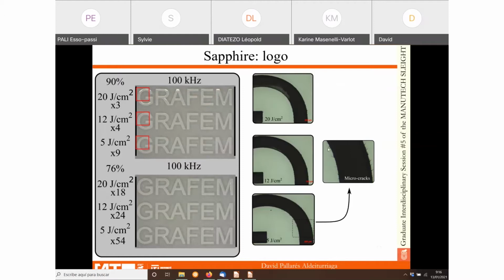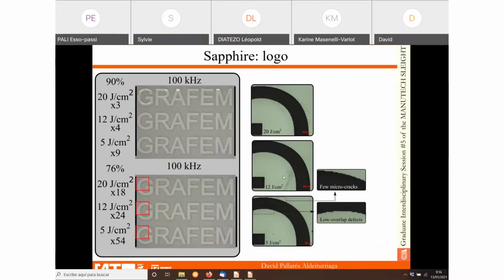There are micro cracks at the edges that are reducing the interest of the inscription. So it will be interesting to get rid of this effect, and that can be done by reducing the overlap. Okay, in such case, that's right, there are no longer micro cracks, but we see another thing in exchange.